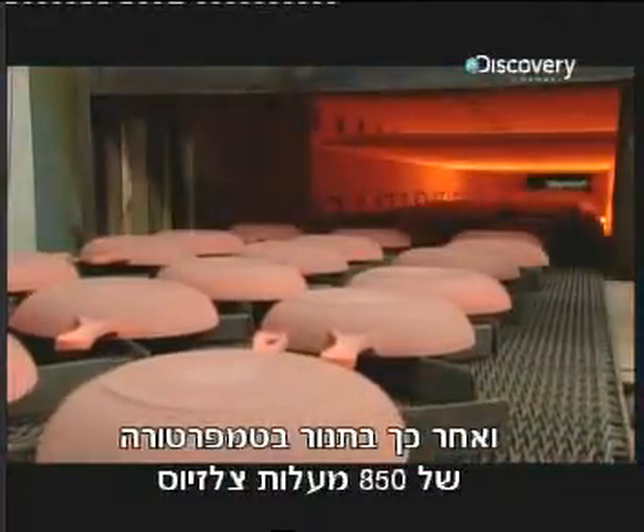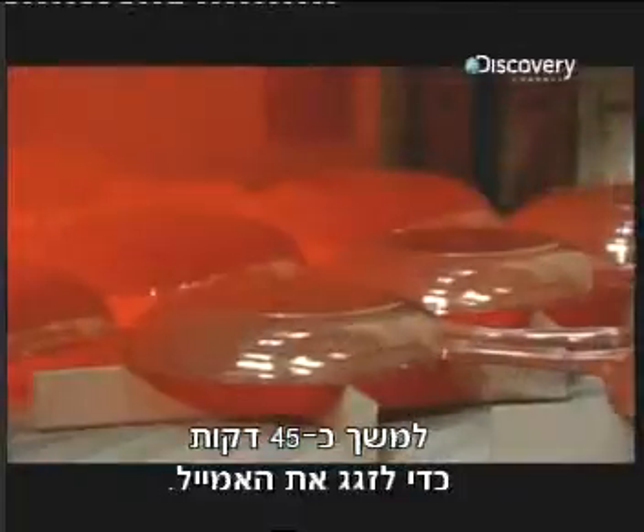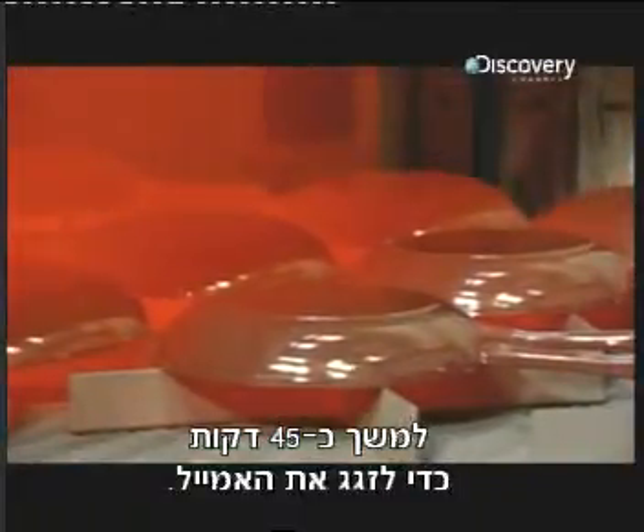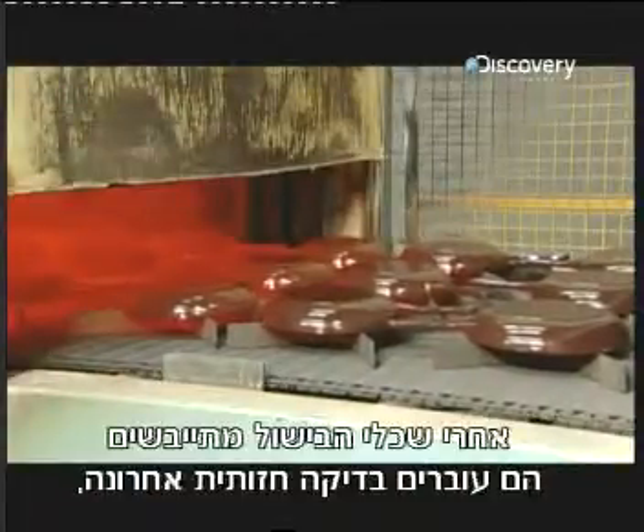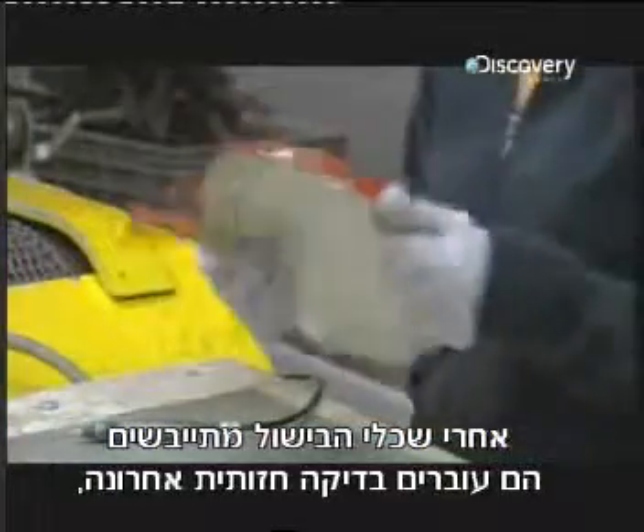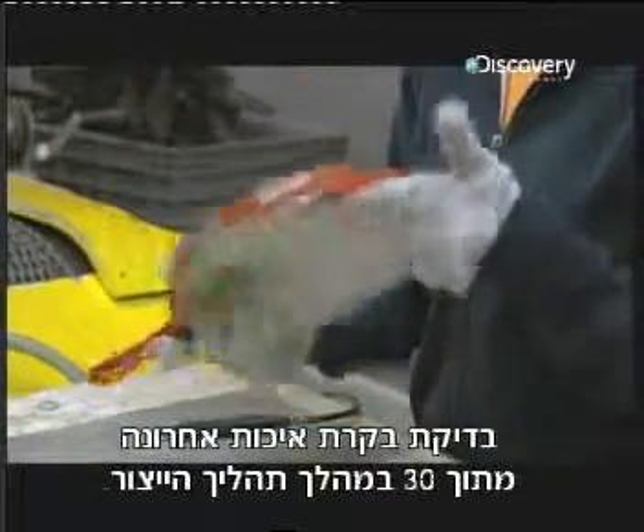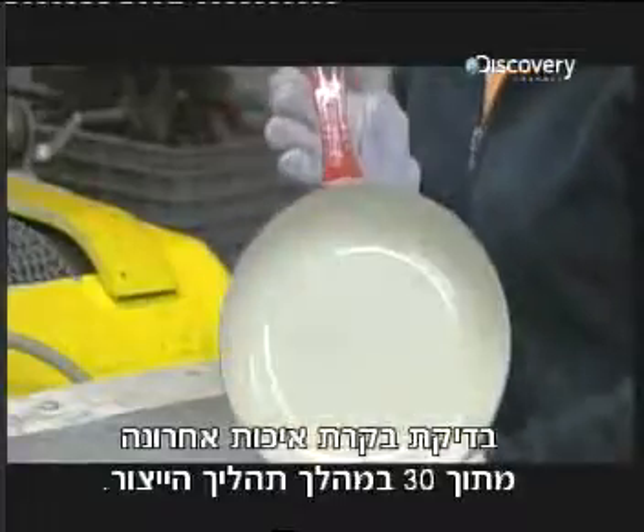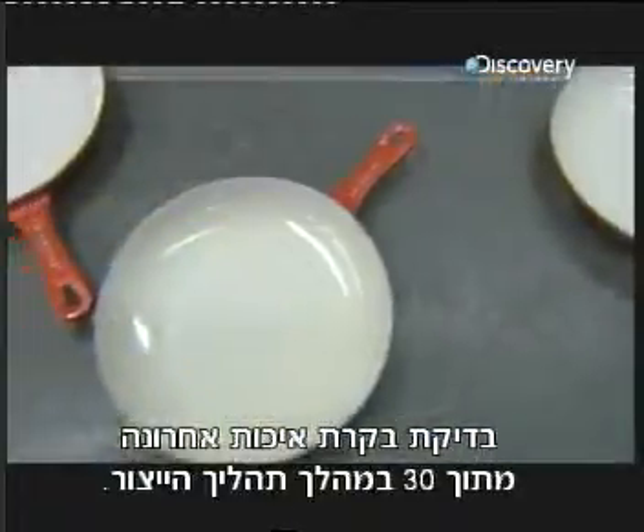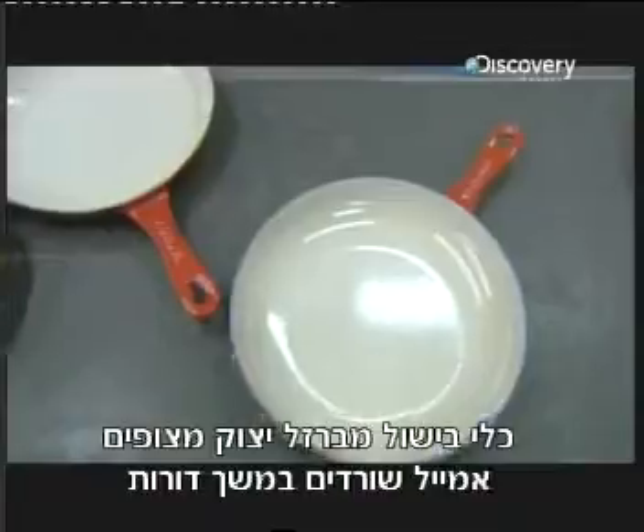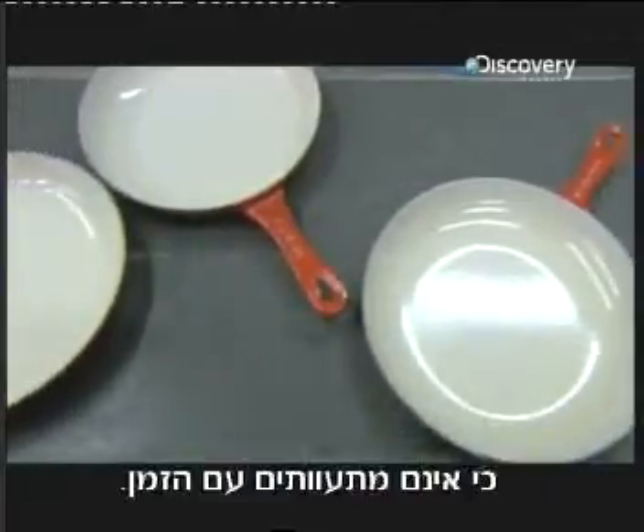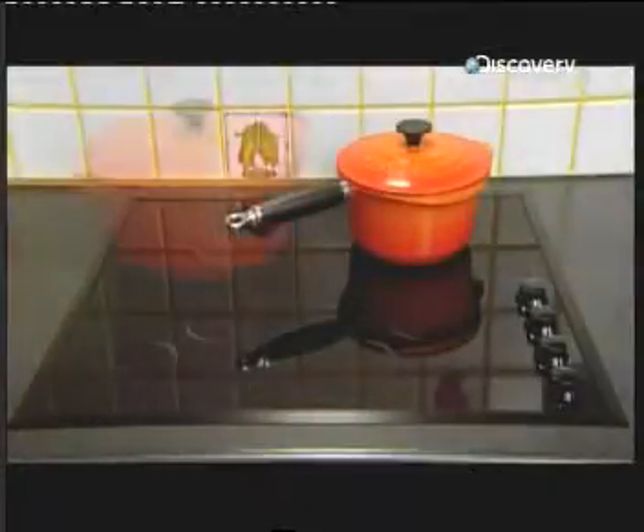Once again, the cookware goes through the dryer. Then into the oven at 850 degrees Celsius for about 45 minutes to vitrify the enamel. Once the cookware cools, it undergoes a final visual inspection, the last of 30 quality control checks throughout the production process. Enameled cast iron cookware lasts generations because it doesn't warp over time.